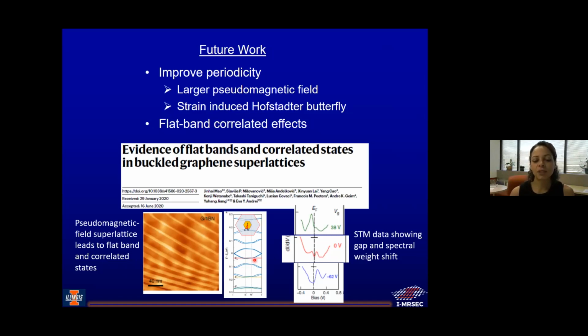Okay, so non-dispersing bands means you have very strongly suppressed kinetic energy, which means that you very likely have enhanced interactions. And so this has been something that's really booming in condensed matter physics, this idea of very strong interactions around the Fermi energy due to what are called flat bands. But flat bands are generally really hard to engineer, okay? But it turns out they may be engineerable in strained graphene like you see here.